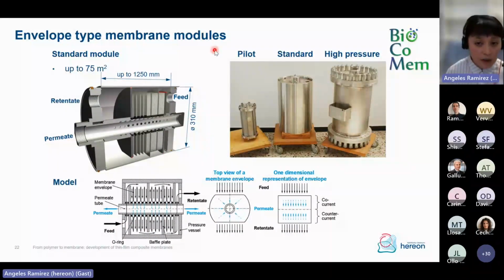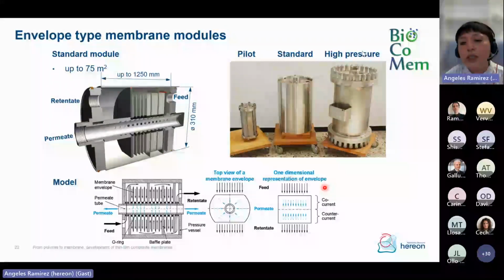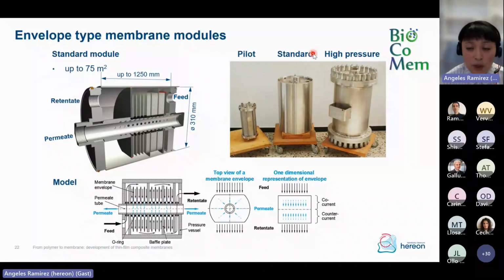Now, we have different types of modules depending on the application. For piloting applications, we have this small module here that allows a membrane area of up to 1 square meter. And then we have these bigger modules, which can house up to 75 square meters of membrane. They will be different depending, of course, on the operating pressure that they can withstand. The standard module can operate at pressures of up to 20 bar, and this high pressure module can operate up to 100 bar.